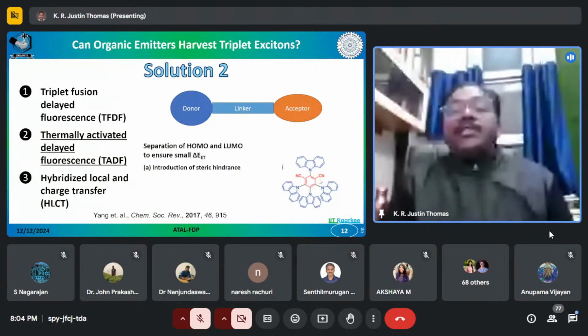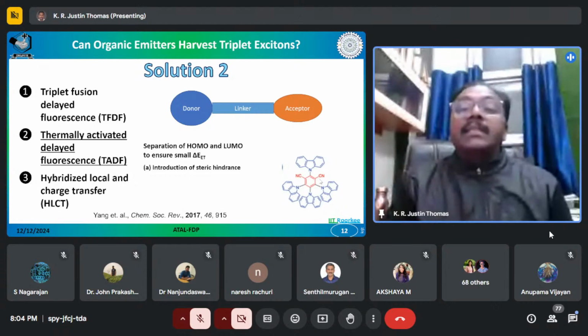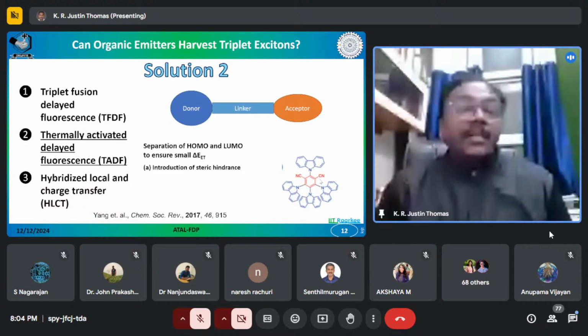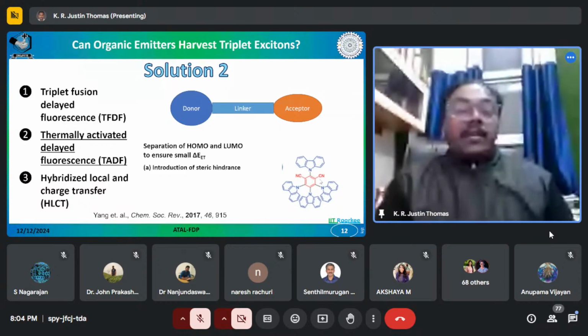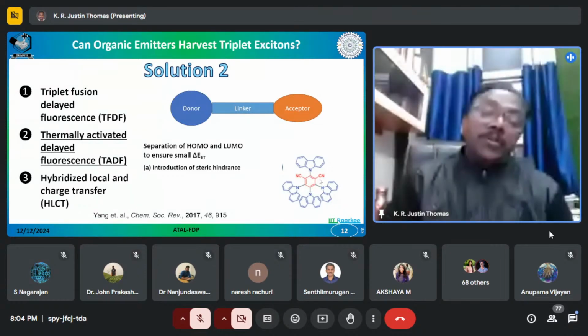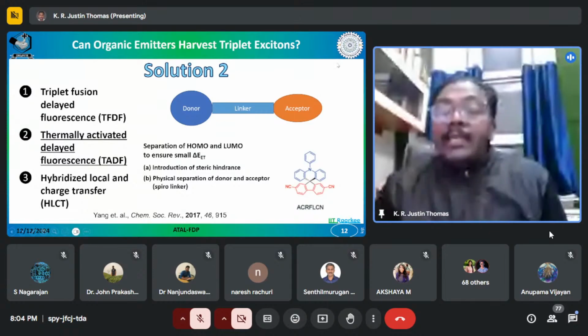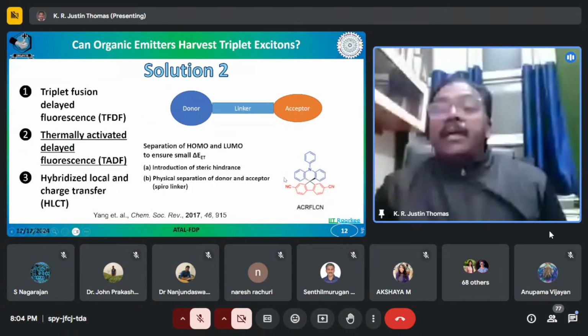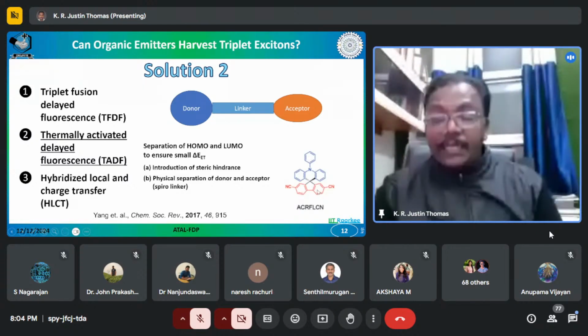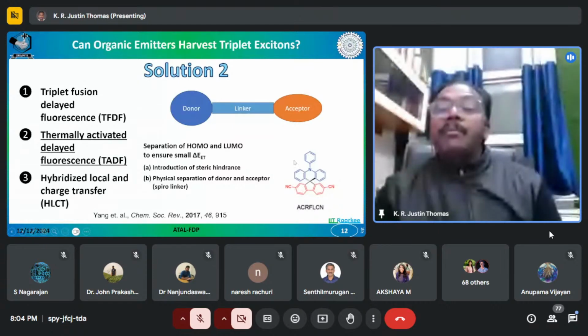Alternatively, you can make a linker which is non-conjugated. In such a case, there is no electronic communication possible between the donor and acceptor. So the donor will contribute to the HOMO, and the acceptor will contribute to the LUMO, giving a well-separated HOMO-LUMO. That is what is seen in this molecule. Here, the segment shown in red is an acceptor unit because it contains two cyano units, and the segment shown in blue is the triphenylamine moiety, which can act as a donor. Since an sp3 carbon connects these two, there won't be any electronic communication. So the HOMO will be mainly localized on this part, and the LUMO on this part.